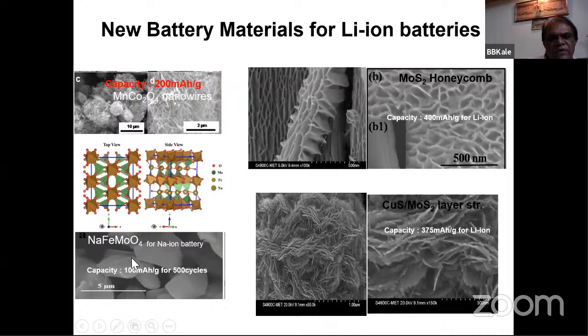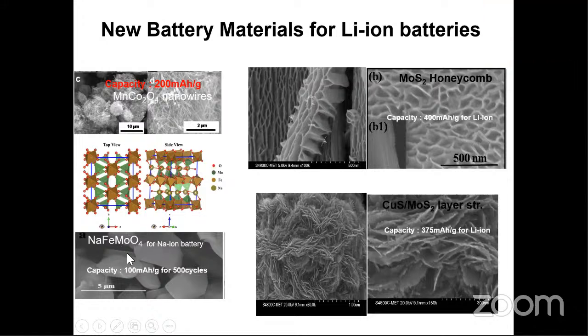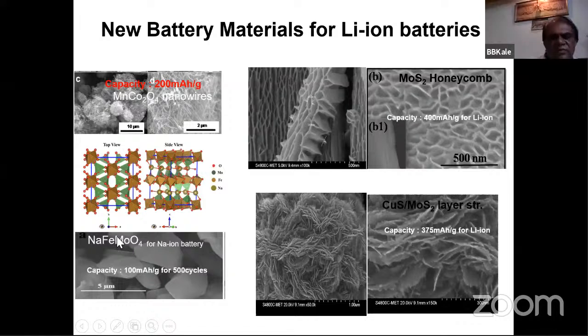Another new class we developed is NaFeMoO4 and LaFeMoO4. These two MoO4 series we invented. We would like to study the crystal structure of both compounds because it is not available. And we would like to modify them a little, because we get very stable capacity of 100 milliampere hours up to 500 cycles for sodium ion. But if you modify this, then definitely it can be increased. Many of our students are working on these MoO4 based materials. One group is working on PO4 based material, one on MoO4 based materials, and another on conventional ones. So we have to keep both in mind and work for better batteries.